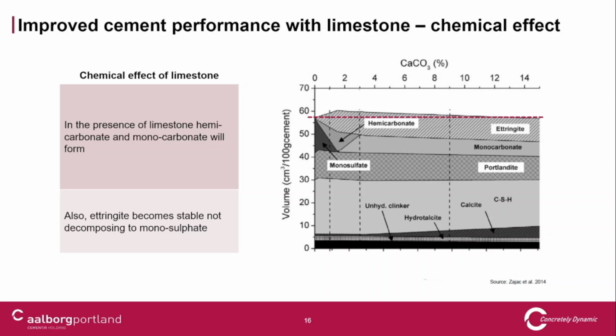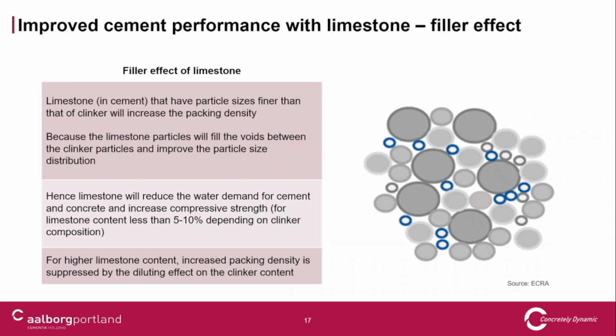What happens is that these new reaction products actually increase the volume formed, and if you have the same confined space, more volume means less porosity. So when this reaction happens, shown by the dotted curve, the total volume of the system is higher, which is why we see a positive influence on strength. Below around 2% calcium carbonate, we have an optimum with the highest influence on strength, and all the way up to around 10% carbonate we can expect a positive influence on strength. The last effect, maybe the most obvious, is that small particles fitting in between larger clinker particles give us a filler effect.